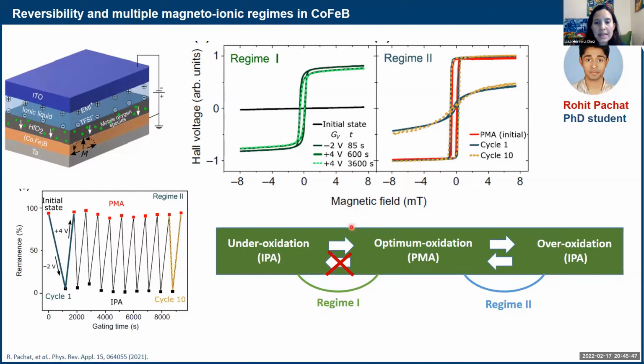So for us, we see that we cannot come back in regime 1, but we can go back and forth in regime 2. So then once again, this probably means that the energy barrier to go back to the in-plane under-oxidized state is much larger than what we can do with the voltages from the ionic liquid. So in any case, it's a very different situation.